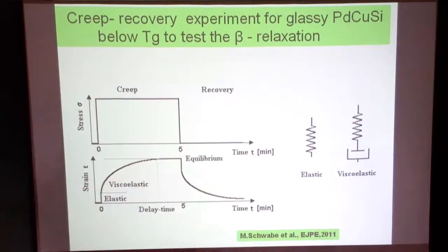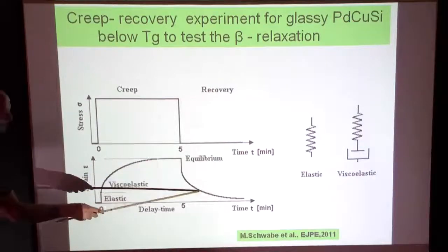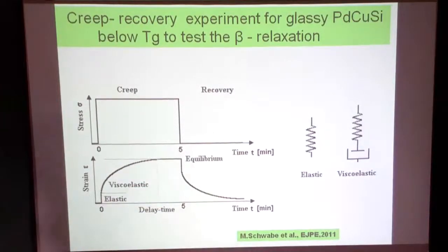So the avalanches which we discuss later on, actually, Kari knows the results, is actually only measured during creep. Whenever you do it actually in recovery mode, purely thermal, there are no avalanches. At least we don't see any. The same is true for indentation. I mentioned in the beginning, you can also make an indentation measurement. You put in really a nanoindenter in the sample and measure then how much you go inside to measure something like a hardness or modulus as well. Going in, there are pop-ins, jumps. Going out, there are none. Okay, so the system behaves very different under stress, mechanical stress, and only thermal.